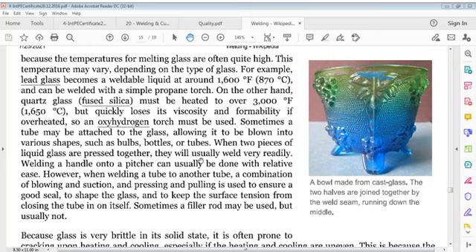On the other hand, quartz glass, which is fused silica, must be heated to over 1650 degrees Celsius, but quickly loses its viscosity and formability if overheated. So an oxyhydrogen torch must be used. Sometimes a tube may be attached to glass, allowing it to be blown into various shapes.